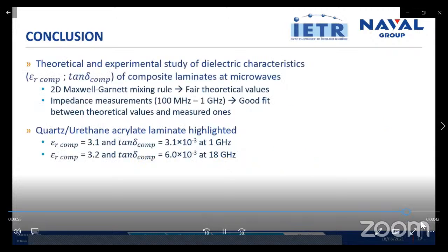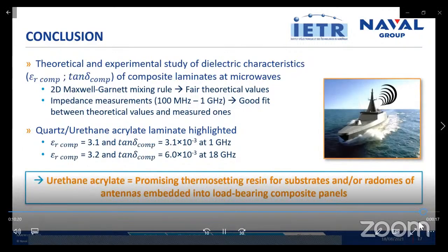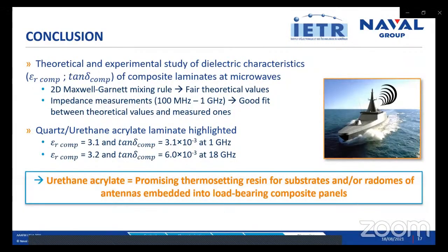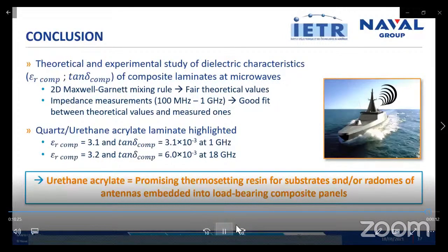To conclude, I presented the theoretical and experimental studies that we conduct on dielectric composite laminates at microwave. From the 2D Maxwell-Garnett mixing rule, we obtained fair theoretical dielectric characteristics. By comparison with impedance measurement results, we obtained a good fit. After showing the dielectric performance of the quartz urethane acrylate laminate, we can conclude that urethane acrylate is a promising thermosetting resin for substrates and radomes of antennas embedded into load-bearing composite panels.